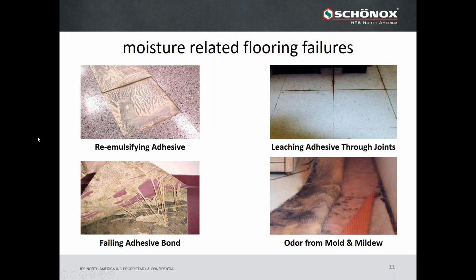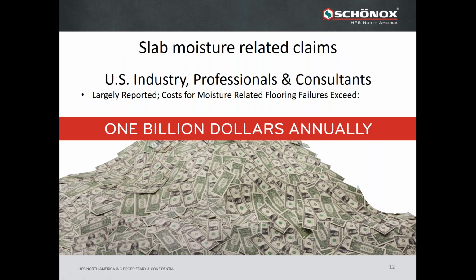We also see it evidenced on a failed floor where the adhesive is actually re-emulsified underneath the finished product, as well as adhesive leaching up through the joints, whether it be solvent-based or water-based adhesive, as moisture migrates up through the joints within a VCT. You'll also see evidence of failure in the adhesive bond to the mechanical bond on the backside of the surface and to the substrate. And finally, with carpeted surfaces, the carpet or pad would have evidence and odor from mold and mildew, which would certainly indicate moisture-related flooring failures.